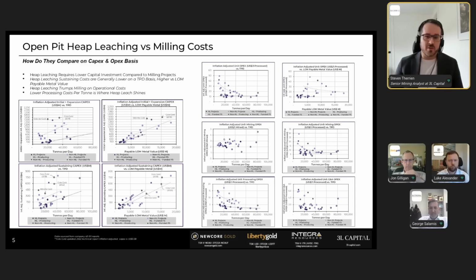So for example, a 30,000 ton per day milling operation might cost around 920 million US, while a heap leach operation of the same scale on tons per day basis might be 225 million. So it's almost a $700 million delta in capex. If you look at it in terms of the life of mine payable metal value, it's still also less capital intensive. Why is that? It's mainly, you don't need the energy intensive high capex mill. There's no liquid solid separation, and there's no tailings disposal at heap leach mines.